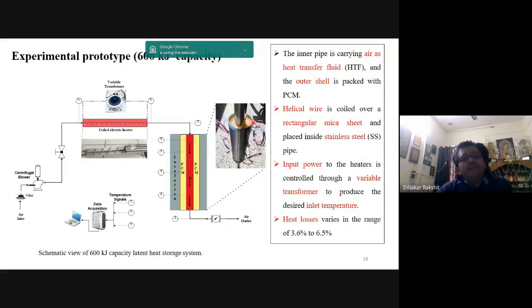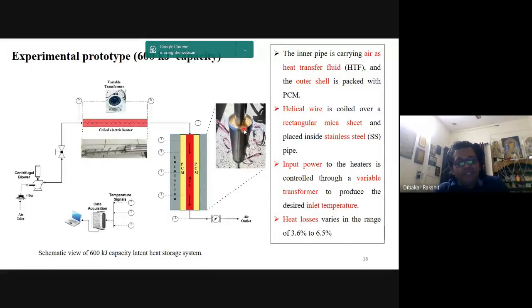As I told you, we made a prototype thermal battery in our lab at IIT Delhi only. It consisted of an inner pipe, which was utilized to charge or discharge. We had a core and shell type of arrangement. The tube, which was the core, had hot air blown through it, and then we had this outer structure, the shell, where we were packing all the phase change material which we wanted to melt, and see how the strength of charging and discharging of that phase change material is.